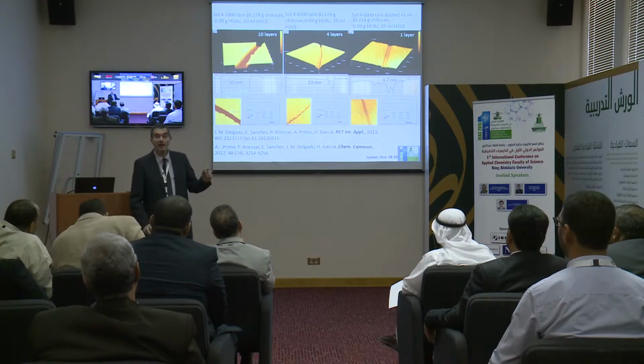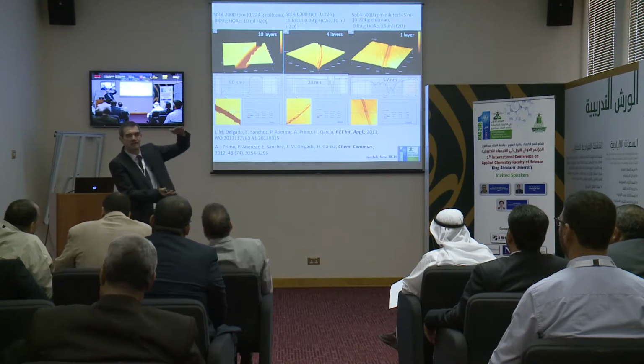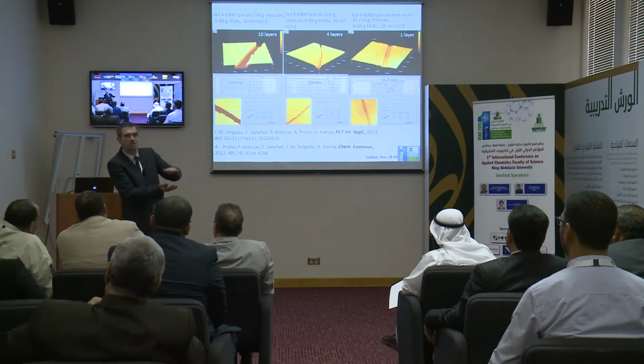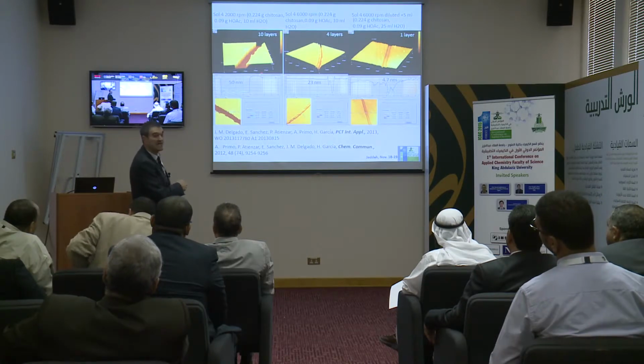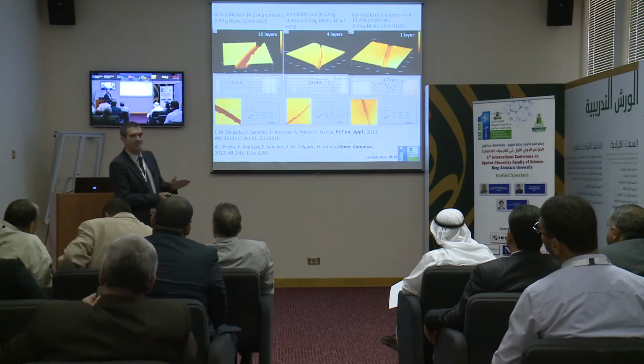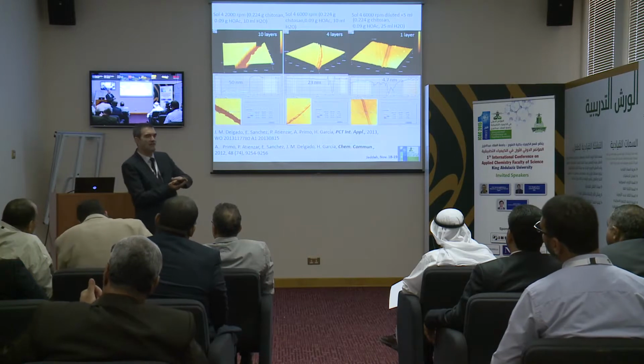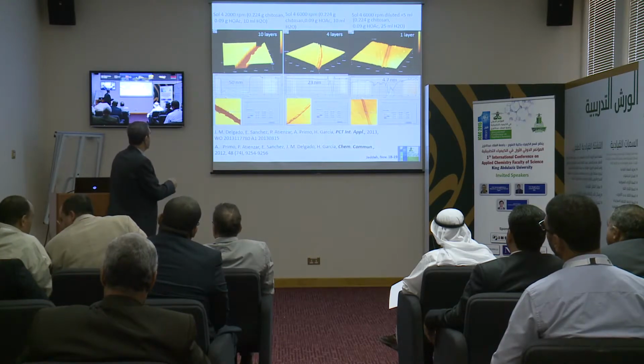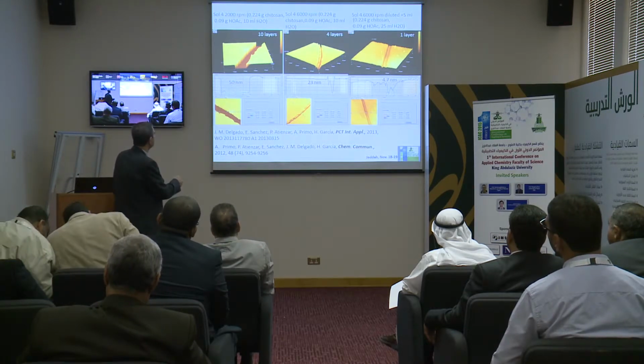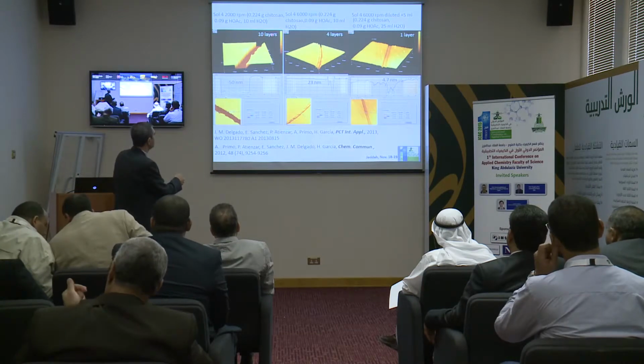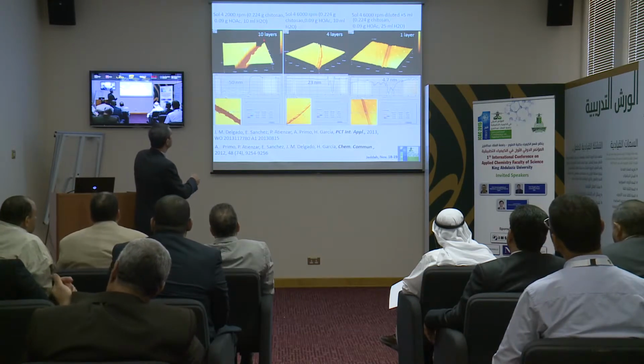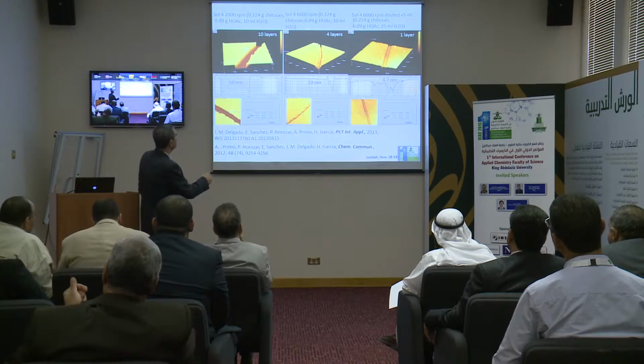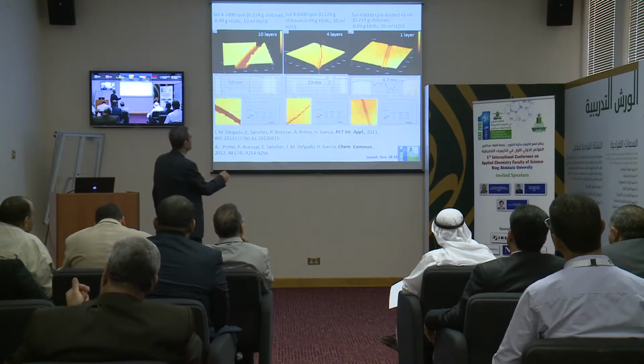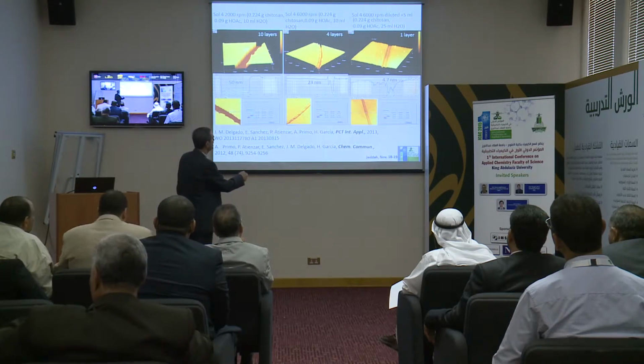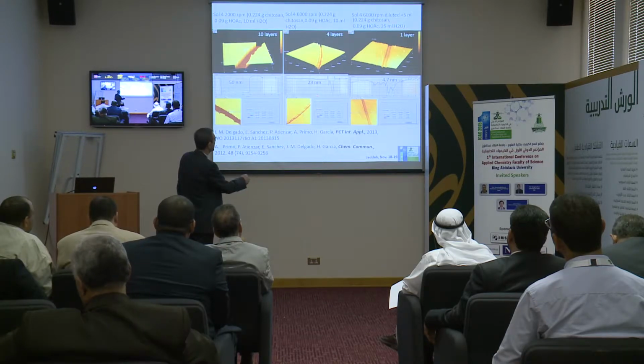And when we pyrolyze, then the film shrinks. So we concentrate a lot. And this is because the structure of these biopolymers changes completely, and now what we have is a flat graphene. And then from 50 nanometers, we have graphene with 10 layers. But we can prepare more diluted solutions. And if we prepare more diluted, then we have here a thickness of 23 nanometers, comparing this height and this height, 23 nanometers. This is the image.